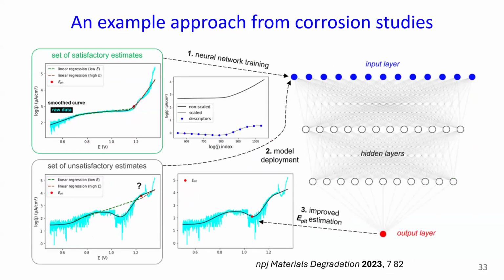and so I can give an example of how this problem has been approached in the field of corrosion research. In corrosion research, the experimentation is kind of similar. It also uses scanning electrochemical cell microscopy. However, instead of measuring catalysis, we're measuring corrosion: as you increase the driving force, you begin to oxidize the surface, which is known as corrosion, and then your current goes up. Again, it's the same problem of how to handle 100 different CVs. We're interested in an activity descriptor, and in this case it's the pitting potential. Here, the pitting potential is defined as the transition between passivation and activity, which you can determine by linear fitting.